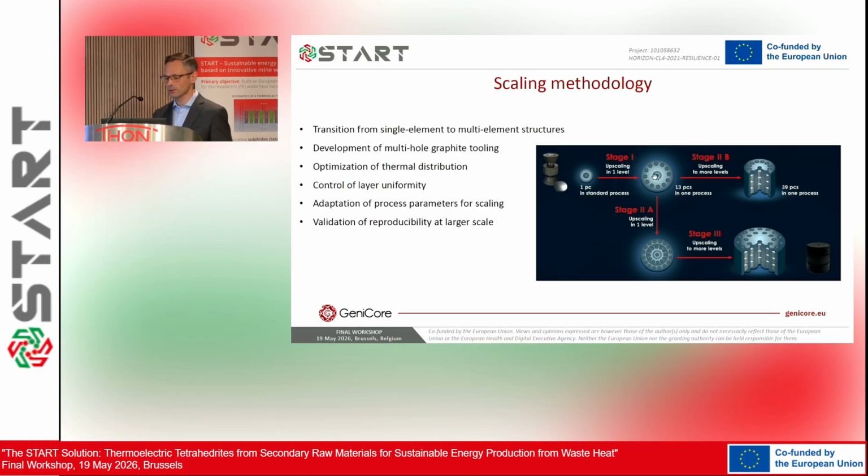At this stage, we use quite the same parameters, in the sense that if for the one-hole system a heating rate of the order of 50 Celsius degrees per minute was needed and the current intensity was 1 kiloampere, it means for the multi-hole system we have to increase only the pulsing, we have to increase the power of the heating system.